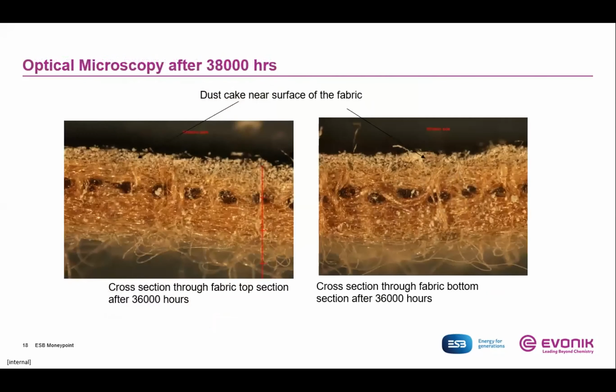And the most important thing is this one. We're talking about 38,000 hours, and still the dust cake is near the surface. The other particles that you see here are most likely accumulations that were transported into this cross section during the sample preparation. But you see here a very thin layer of dust, which is just accumulating near the surface of the fabric.